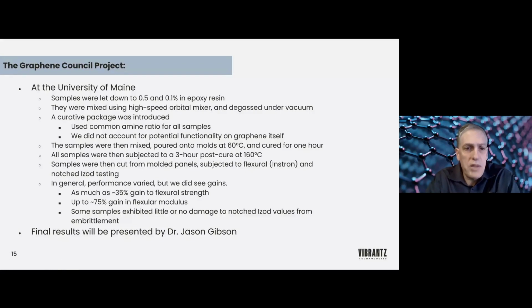The samples were then mixed, poured into molds at 60 degrees Celsius, and cured for 1 hour. They were subjected to a 3-hour post-cure at 160 C, and then the specimens were cut from molded panels and subjected to flexural, Instron, and notched Izod testing. In general, we saw the performance varied, but we did see some gains, as much as 35% gain in flexural strength, up to 75% gain in flex modulus, and some of the samples exhibited little or no damage to notched Izod values from the resulting embrittlement of increasing the rigidity and modulus of the material.